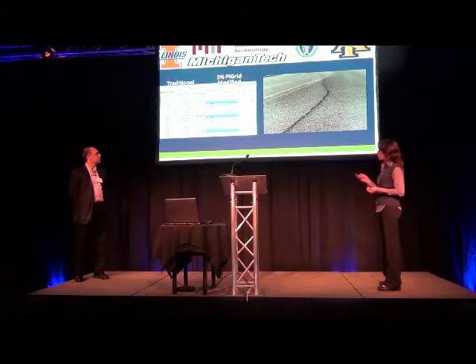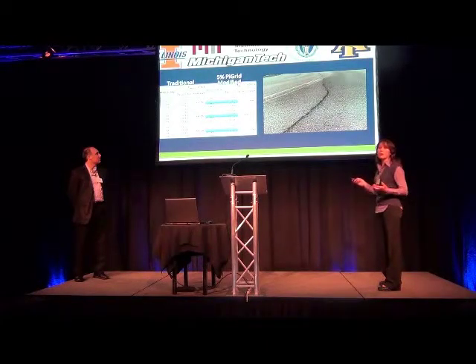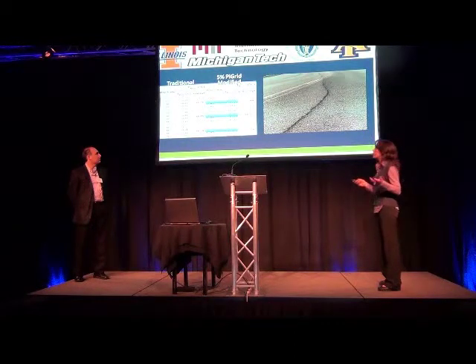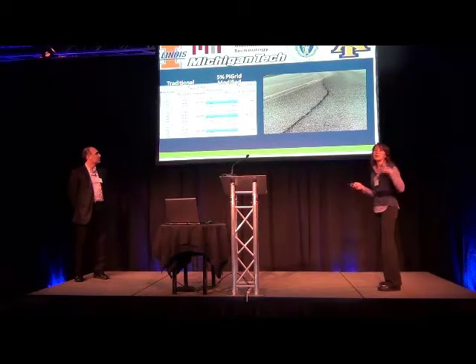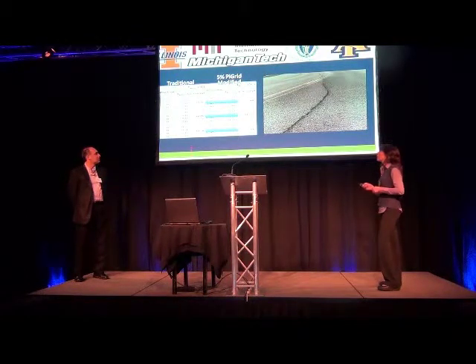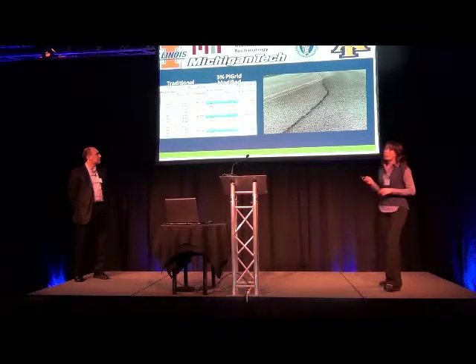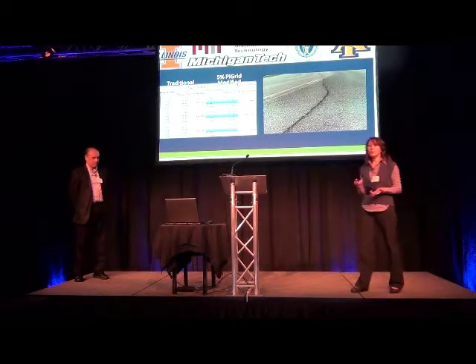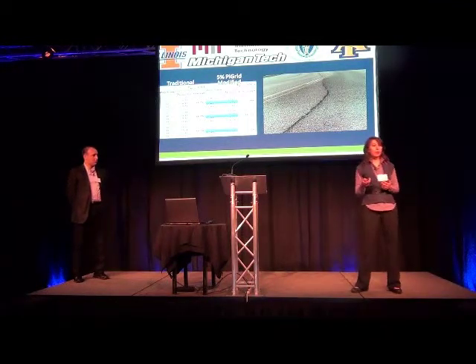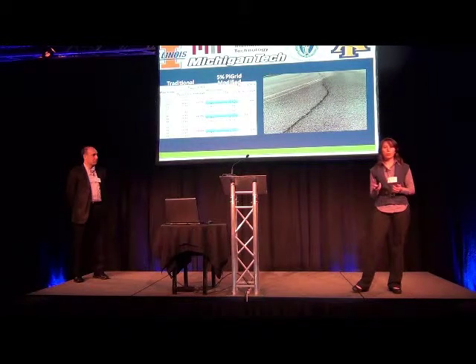And you can see this is significant in terms of states in colder regions, like Massachusetts, Pennsylvania to some extent, but Michigan and northern states that get very cold. We can reduce the cracking, which actually ends up being potholes sometimes after that. With increasing the cracking resistance, we found out we can also use recycled material more and more.